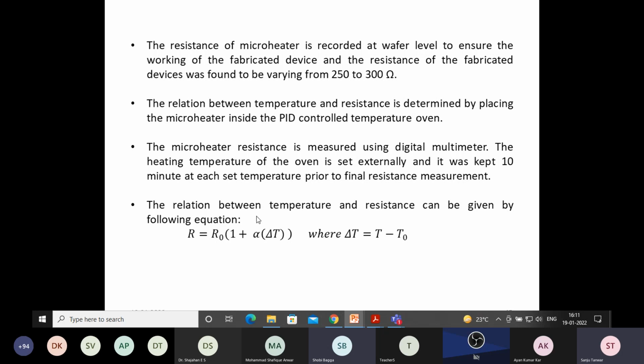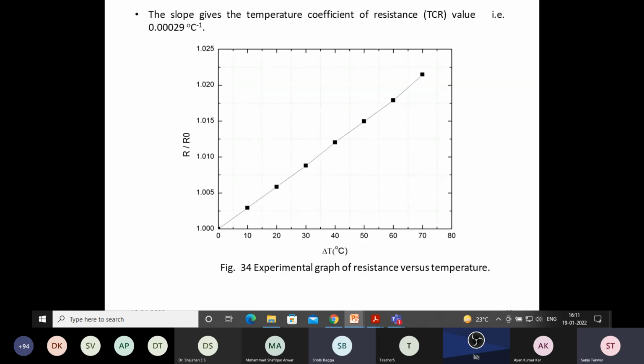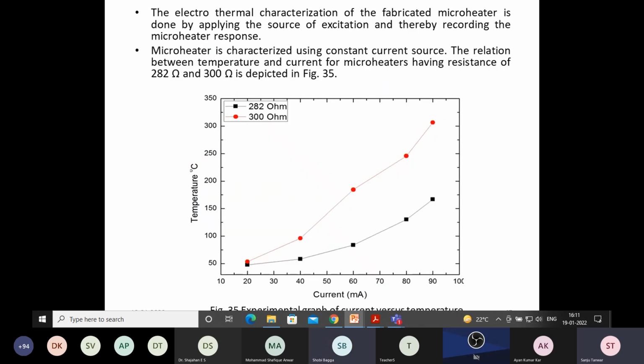And then the relation between the temperature and the resistance is given by RT equals R0 into 1 plus alpha delta T. So what we have obtained is R by R0 versus the temperature, which is approximately a linear relation. And the slope of this is basically giving me the TCR of approximately 0.00029 per degree centigrade. That is temperature coefficient of resistance. And electrothermal characterization of the fabricated device is done.